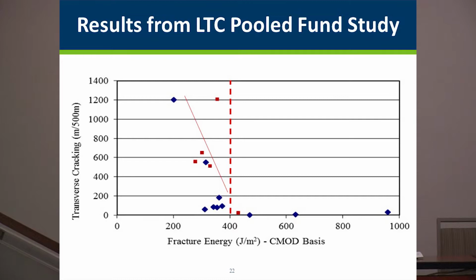This shows the results that we got. Again, the idea of the high fracture energy with the 400 joules per meter squared. You can see how when we had low cracking, you had high fracture energy. When you had high cracking, you had low or lower fracture energy. So that really showed how we came up with the criteria that we have been using.